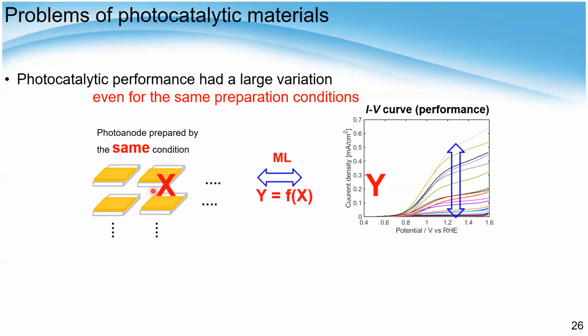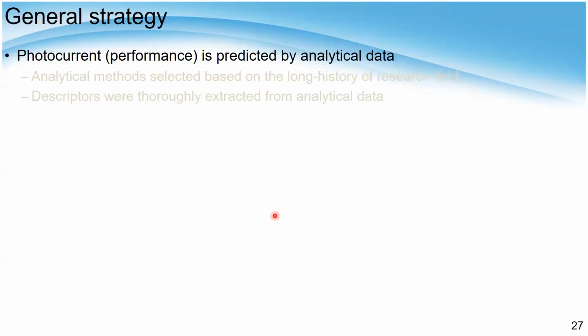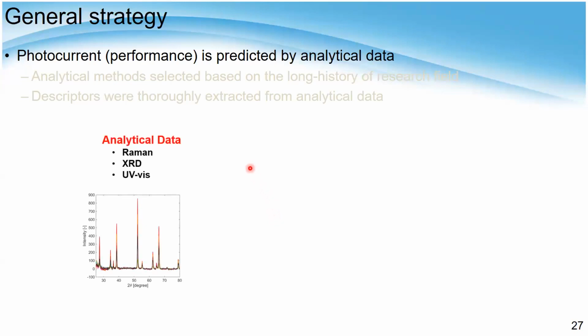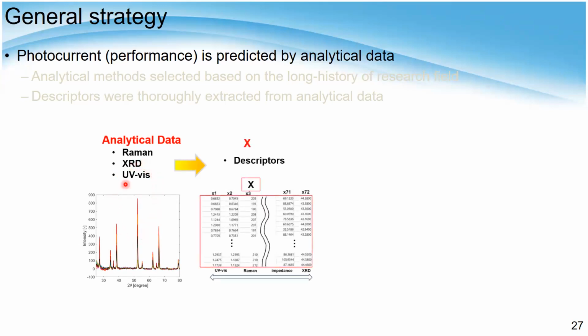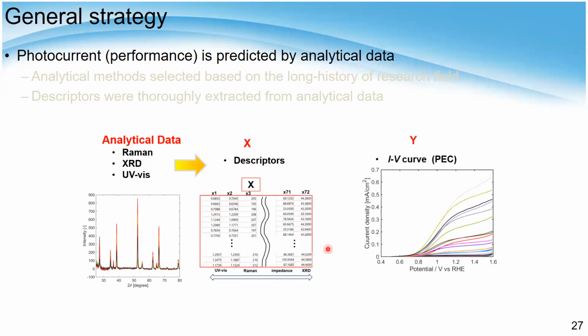But in this case, experimental conditions are totally the same, meaning that the X is the same, right? So from the same X to various Y cannot be predicted by using a function. So a function itself cannot be generated like this. What we did actually is we collected analytical data for these materials, such as Raman, XRD, and UV-vis. And from these analytical data, we generated the descriptors X, and then predicted the PC performance by using machine learning.